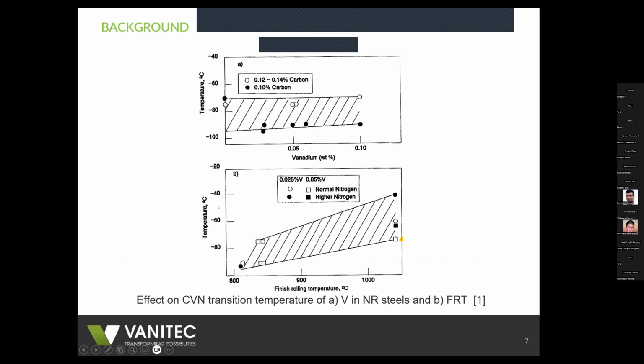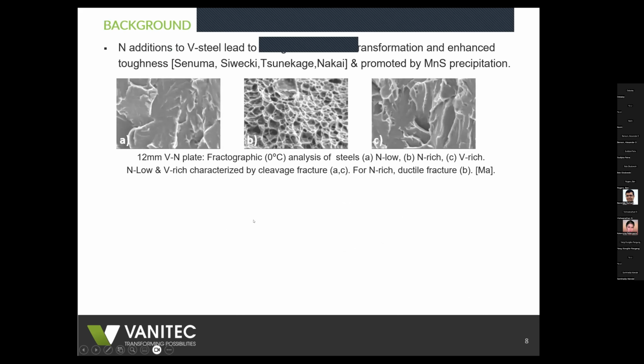These are graphs just showing the influence of vanadium content versus transition temperature. You can see pretty good results over a wide range of vanadium contents. And the bottom graph showing the finishing temperature over quite a wide range as well. Even as high as above 1,000 degrees, it's still going to give you a transition below -40. Yeah. But this is for, yeah.